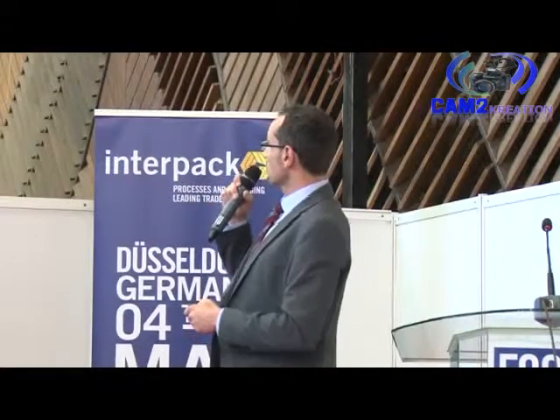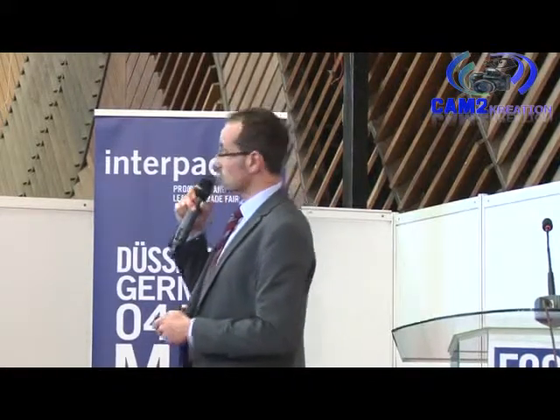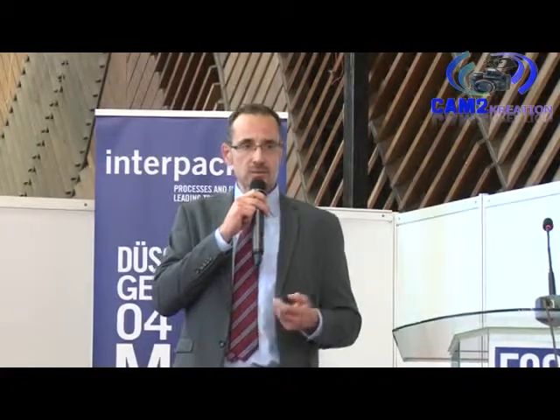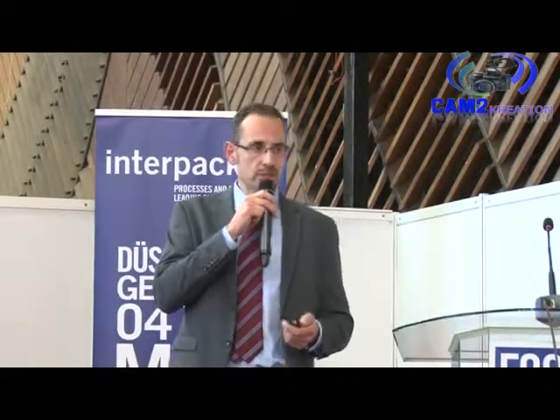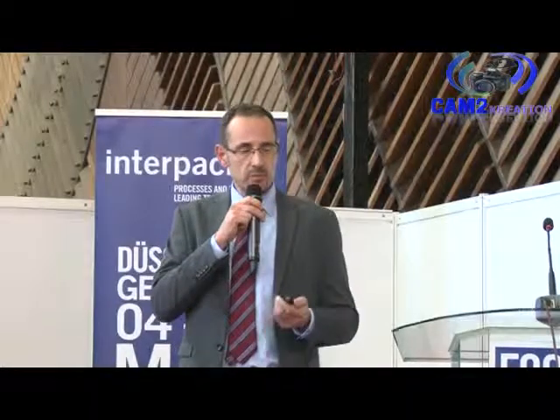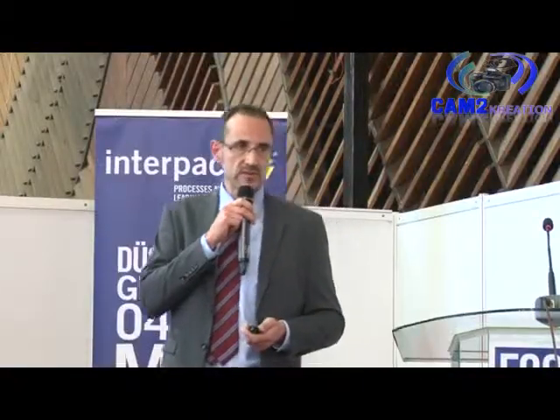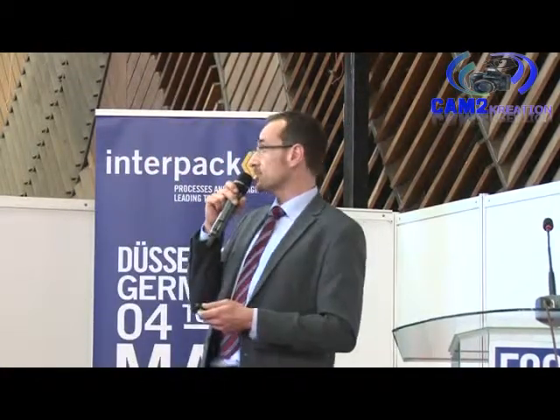And the third process is the so-called cast film extrusion, actually an oriented process. It means this is a product, some of you may know BOPP, BOPET, and this is more or less the same from the process point of view, but it's based on nylon. And this is a film which has very, very high puncture resistance, flex crack resistance, and can be used for vacuum pouches for vertical form fill seal application.